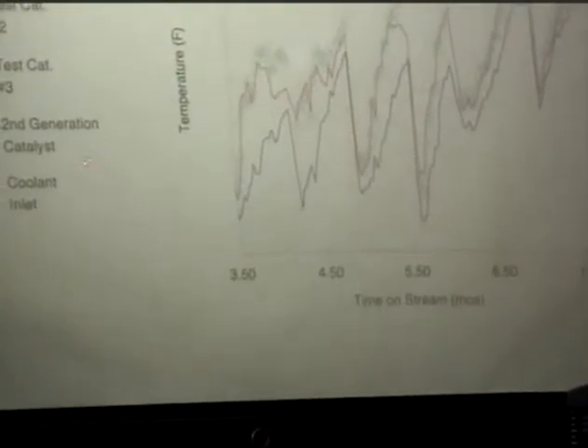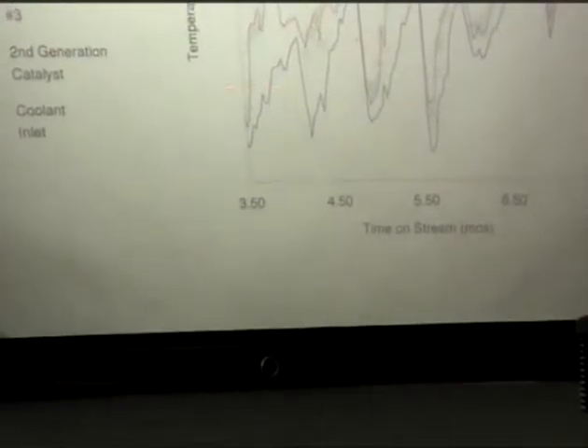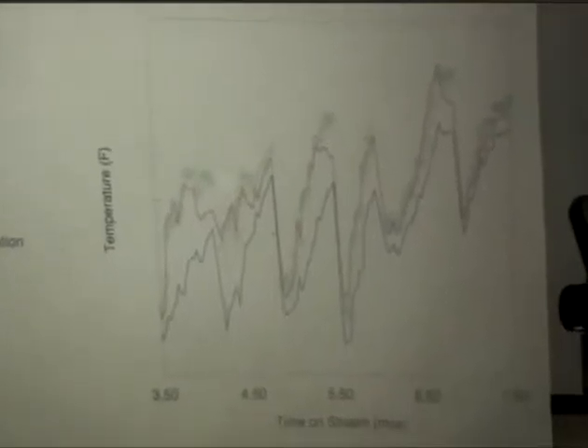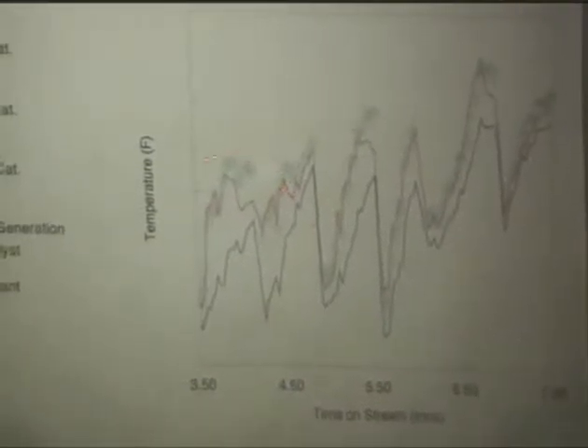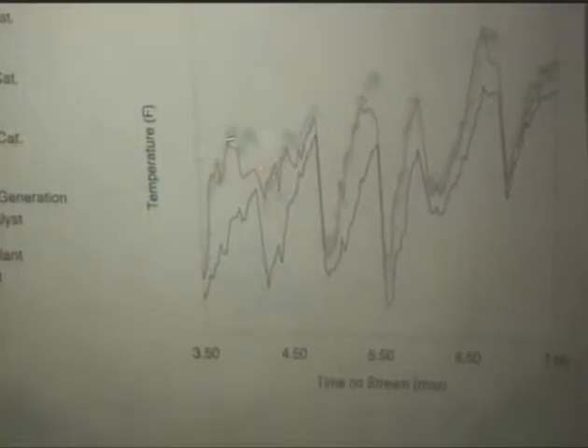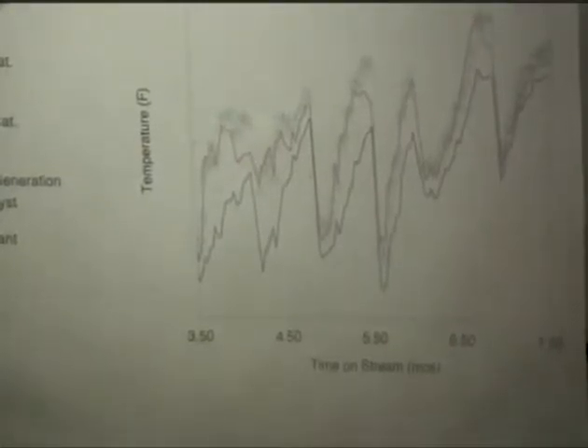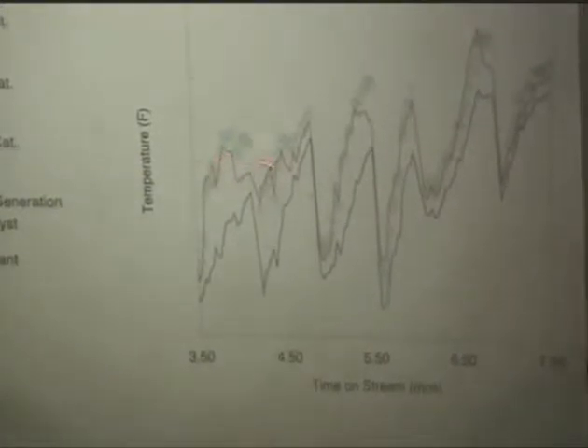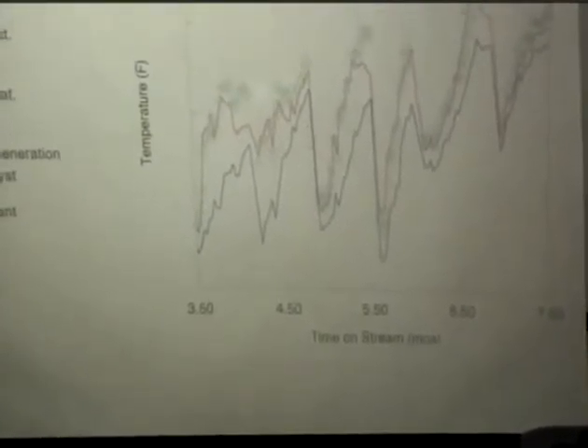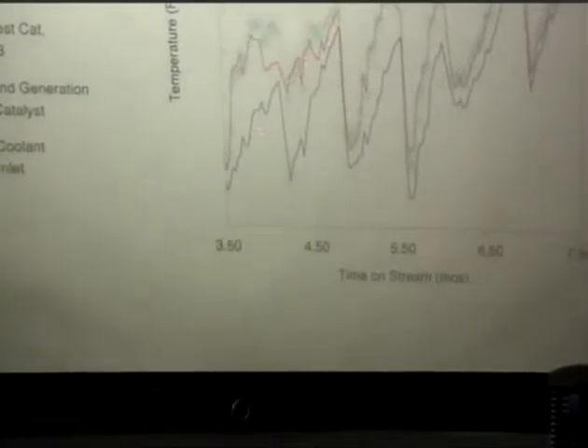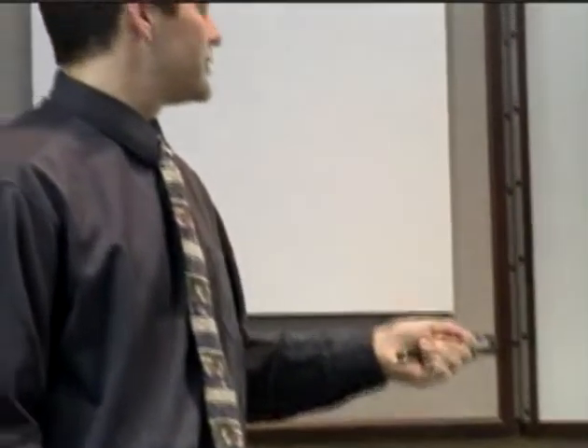So as the catalyst deactivates with time on stream, we raise temperature, which is not too unusual. But you can see that in comparison with the second generation catalyst, actually our third generation samples were performing better at the end of that regeneration cycle. In certain cases here, here, here, here. So we had the impression that, again, we could mimic the performance of the catalyst, but there may be also a performance enhancement with this material.